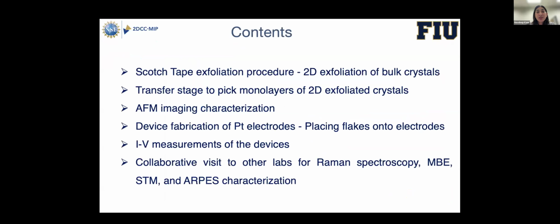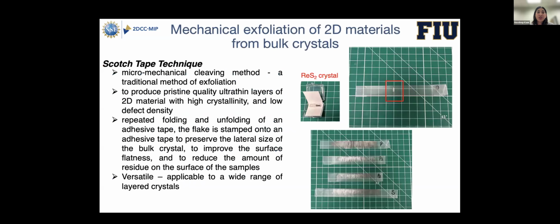And I learned the Scotch tape exfoliation procedure and learned how to use the transfer stage to pick the monolayers or multi-layers of exfoliated materials, and did learn how to do the AFM imaging to estimate the thickness of the layers that we exfoliate. And we also tried to fabricate devices out of it to understand the electrical properties of the materials. And during my visit there, I learned the Scotch tape technique, which is basically the traditional method of doing the exfoliation from the bulk crystals to obtain the monolayers of the materials.